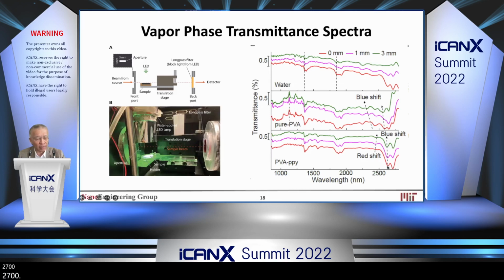You can see 2,700, right? And that's the vapor water spectrum. And you can see as you go higher and higher on the surface, a blue shift. And that's because the water cluster becomes smaller and smaller. So this gives us a lot of insight, and we believe that this is a photon effect and a surface effect.